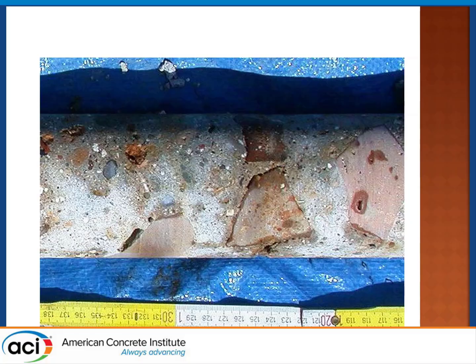This is a core, right? Good thing I told you that. It's not so much interesting. It's gap graded, proof that the Tarantula curve is not new. And this structure core was removed from the port of Trajan, where it's been sitting in the Mediterranean for a couple of thousand years. Looks like conventional concrete to me. There's no Portland cement in it at all. We've done it before. We can do it again now. Of course, they had different labor management practices that they could use. And all of this concrete was rammed in place like Franki piles.